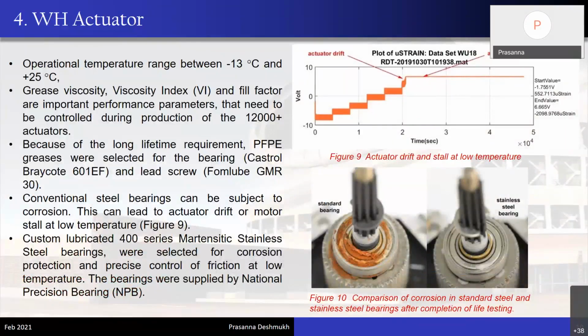Further, an operational temperature range between -13 to +25 degrees Celsius was simulated inside the environmental chamber so as to control temperature and humidity. What we observed is that the grease viscosity, grease viscosity index and the fill factor of the grease within the bearing are very important parameters. If we have a little less grease or more grease, the wear and tear factor changes. As you can see, in one case our previous actuator stalled on one of the operational cycles, and it basically drifts.